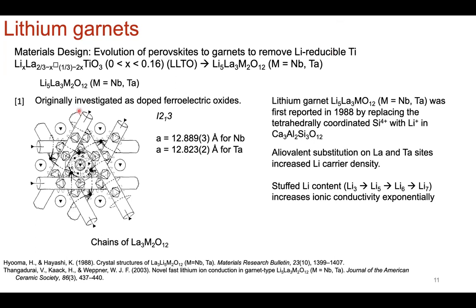So the original X-ray diffraction that looks at this type of material, you can see the outline of this cubic structure where you see chains of lanthanum, niobate and tantalate with the lithium in between this sublattice. Now, then you start substituting in, so then you have the tantalum and the niobium. Then you start stuffing the parent phase of lithium-3, lanthanum-3, M2O12.